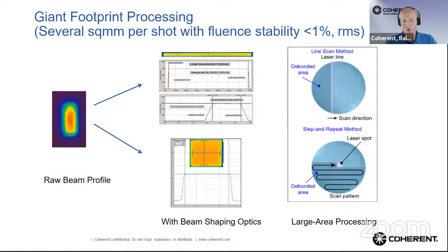So you see the raw beam profile on the left, and then the beam shaping optics shape a very homogeneous line, which is essentially an extended rectangle, because also the short axis is flat top, or a square or rectangle. And then you can do two basic approaches, for example, in this wafer case: you can scan a line over the wafer, or you can do a step and repeat and meander back and forth with a square field.